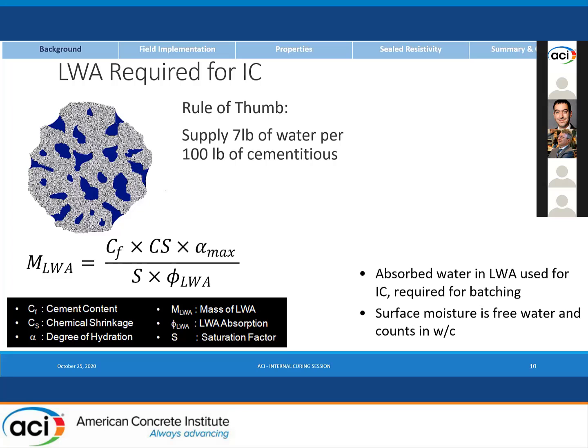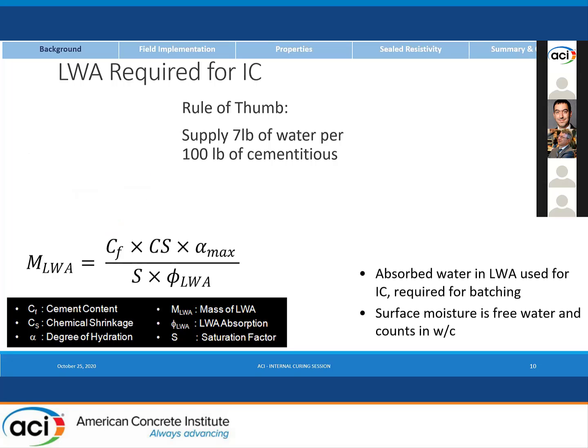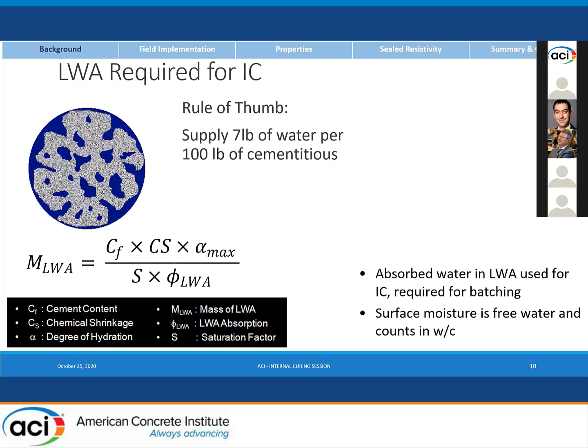There's a rule of thumb of about 7 pounds of water per every 100 pounds of cementitious materials that we're going to hide inside of the lightweight aggregate. I've got here for you the Bentz equation that's been around for a while, so hopefully most are familiar with it. But there are considerations that we need to look at when we're talking about in the field and actually doing this at production scale. So we don't have a perfect aggregate that is in SSD condition.